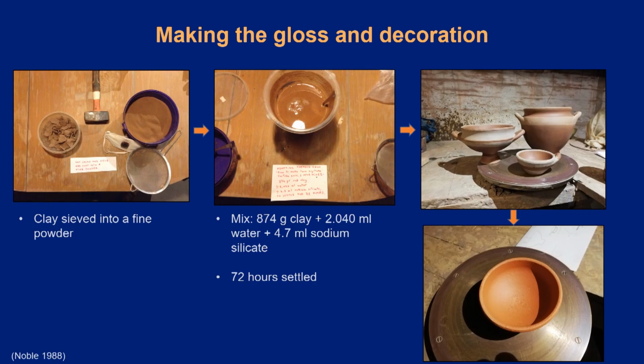In order to replicate the black gloss of black gloss wares, we sieved the clay into a fine powder. Following our references, we mixed 874 grams of clay, 2,040 ml water and 4.7 ml sodium silicate. We left the mixture to rest for 72 hours, then we siphoned the upper and finer solution, then we boiled it to evaporate and produce a dense consistency. Finally, we applied it to the surface of the pots with a brush or by dipping the pot into the slip. We aim to turn it into black gloss after creating a reducing atmosphere at the final stages of firing.